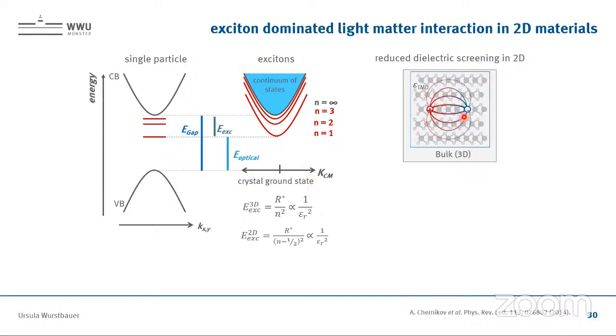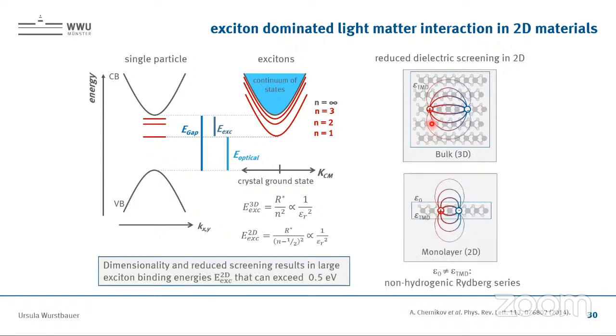And due to the screening of the electric field, the energy of the exciton is proportional to one over the square of the dielectric environment. And with that, the dielectric environment is important. And if you now think about a 2D material, the dielectric environment is highly tunable because this material is so thin. You can have an insulator, then screening is drastically reduced, and with that we have a high binding energy. If you would have a metal in the surrounding, you can do it just by preparing it like that. Then the screening would be drastically enhanced, and with that binding energy dramatically reduced. So meaning here we have really access to the energetics of this composite boson.